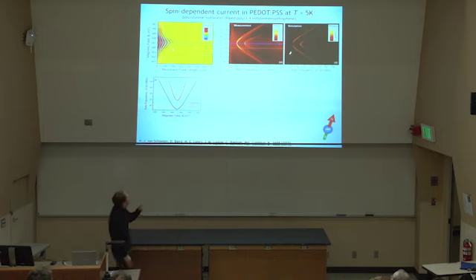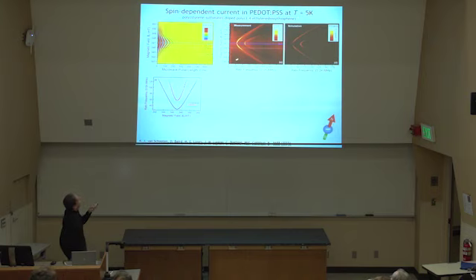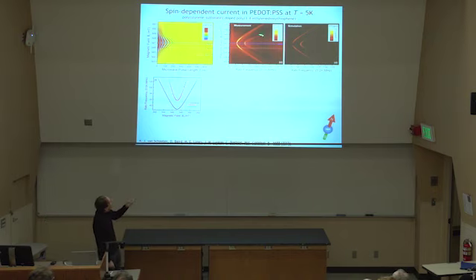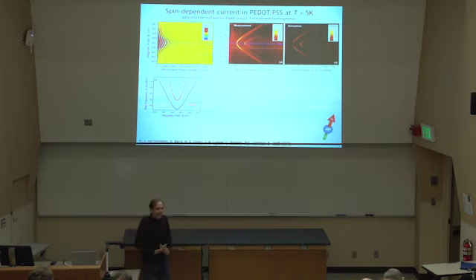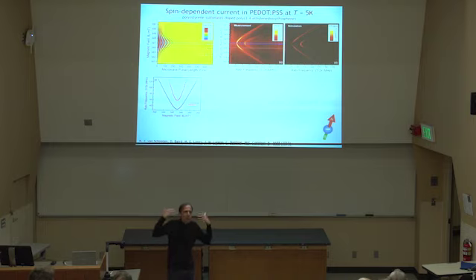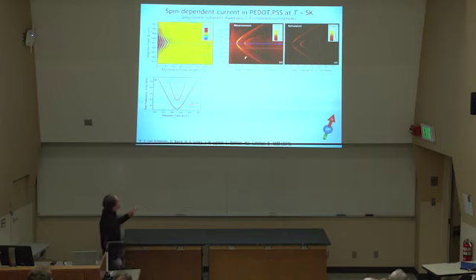You see here, and this is low temperature data though, at low temperatures when you decrease the mobility sufficiently such that electronic transitions become sufficiently slow, you see the imprint of all sorts of Rabi oscillation components. Here's again the Fourier transform, and now you see these Rabi hyperbolas very, very pronounced, which again is remarkable, that a polymer thin film device shows this behavior in its current. In principle, you can do these kinds of experiments with organic electronics that you carry around in your pocket. And again, you learn something about it.